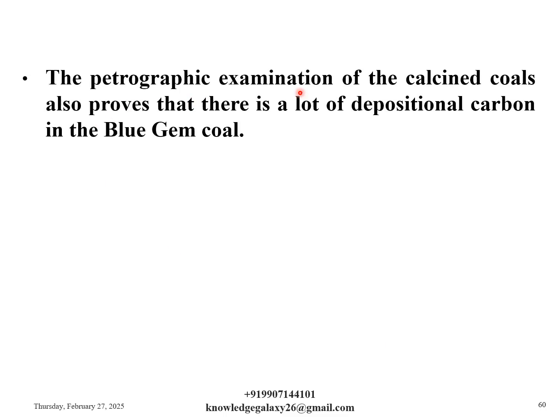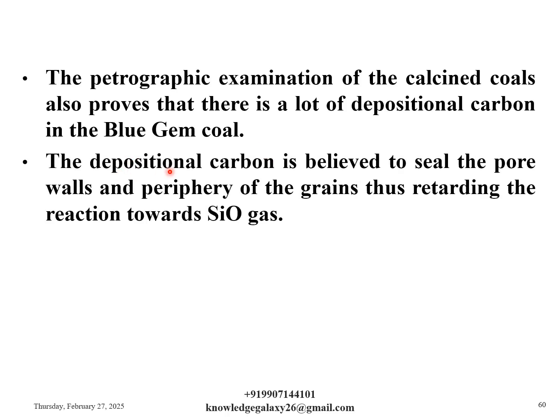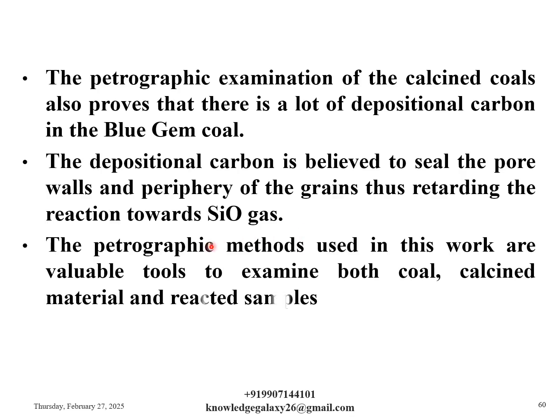The petrographic examination of the calcined coals also proves that there is a lot of depositional carbon in the blue gem coal. The depositional carbon is believed to seal the pore walls and periphery of the grains, thus retarding the reaction towards SiO gas. The petrographic methods used in this work are valuable tools to examine coal, calcined material and reacted samples.